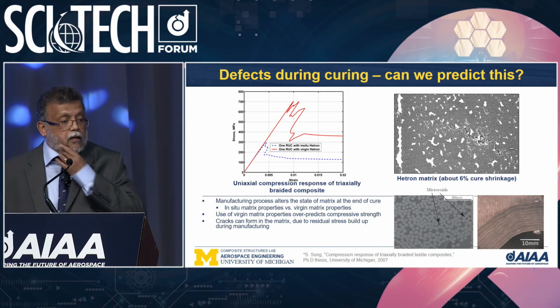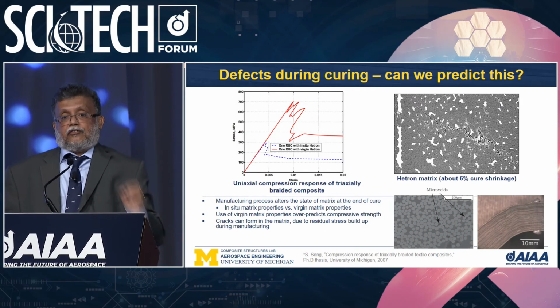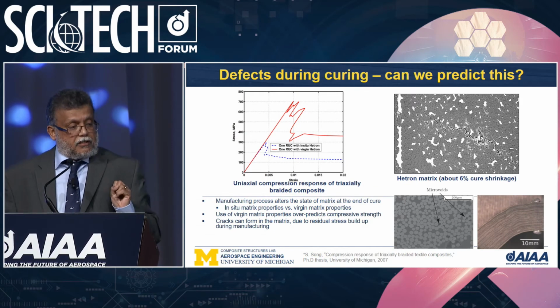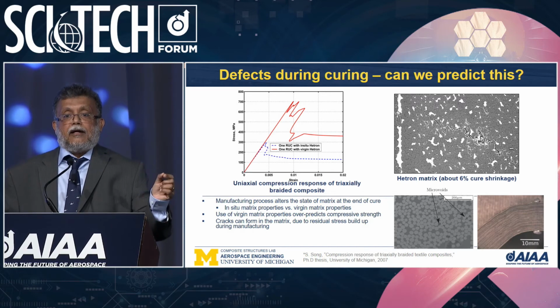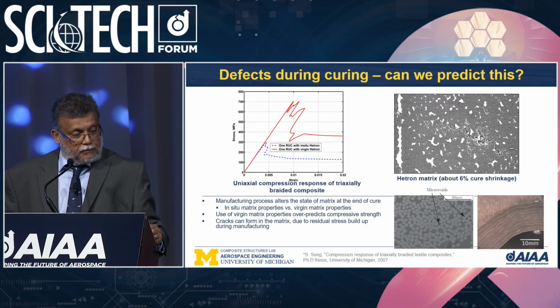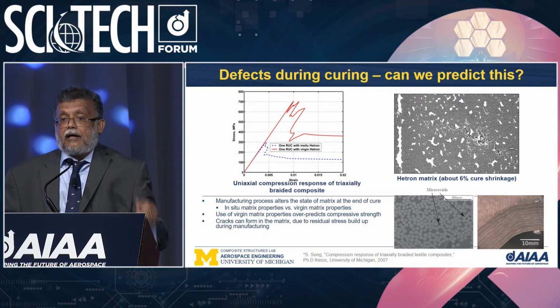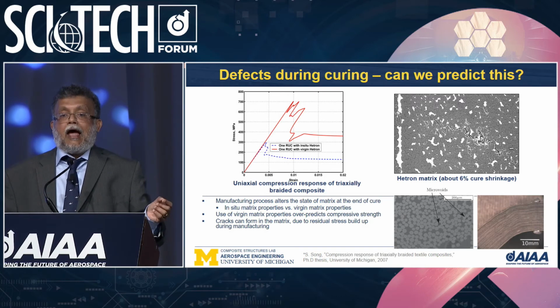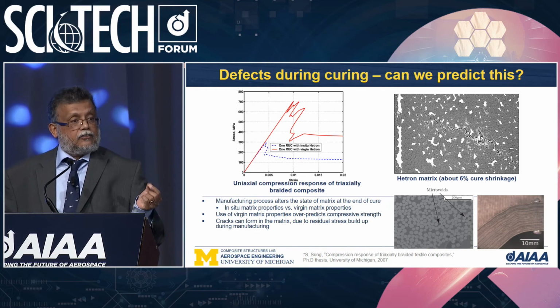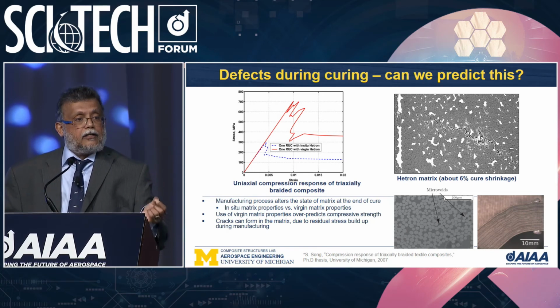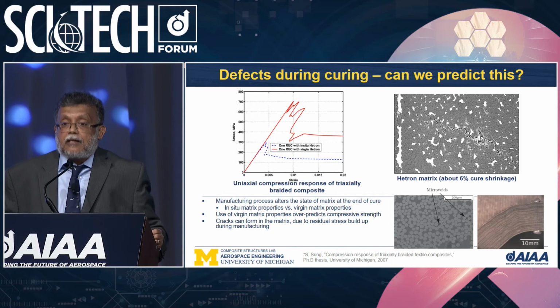All right, what else? You get defects. If the residual stresses are high, you can have cracking inside the structure before you put it into service. You can have wrinkling of plies, and you can have porosity if the gases within the resin at cure are not able to escape.